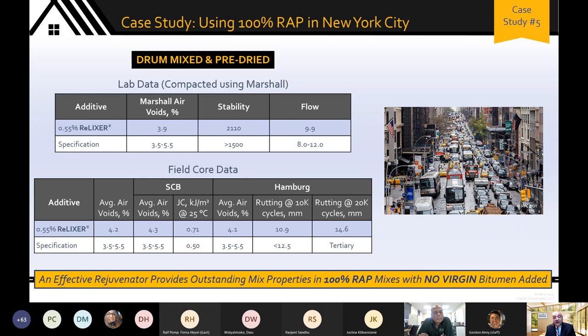Went back after about a year, extracted field cores, looked at SCB, semicircular beam bend, as a measure of our fracture toughness property, and looked at Hamburg as a measure of rutting properties to help them put down really a spec. So it is possible to go all the way up to 100% wrap, a very challenging manufacturing operation, but nevertheless can be done. And this is really the limiting case. If you ask yourself, softer grade bitumen, for example, it will work fine, but there is just no way softer grade bitumen would be able to, in the dosage considerations used here, work in a situation like this. So all materials, all the rejuvenators that I listed previously, they have their pros and cons. They have their place as you begin to evaluate your options for rejuvenation.